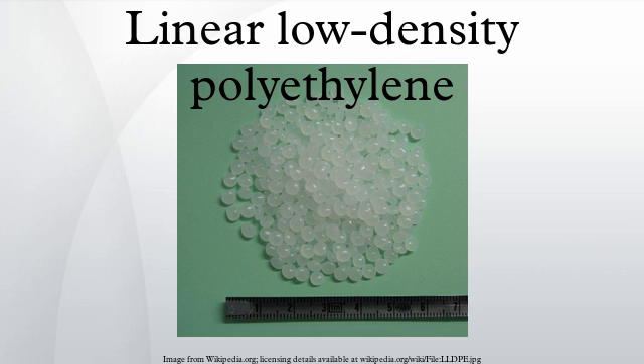Processing: LLDPE and LDPE have unique rheological or melt flow properties. LLDPE is less shear sensitive because of its narrower molecular weight distribution and shorter chain branching. During a shearing process such as extrusion, LLDPE remains more viscous and, therefore, harder to process than an LDPE of equivalent melt index.